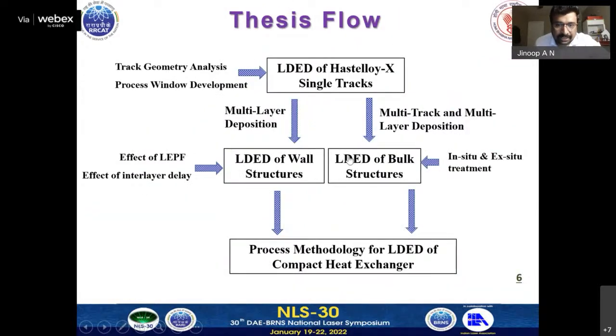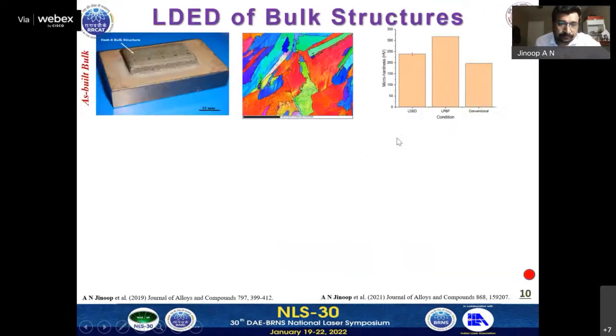Then the next study is on the bulk structures. Bulk structures are structures which are made of multi-track and multi-layer deposition. So for the bulk structures, we did multi-track and multi-layer deposition, and then we cut the cross-section and analyzed the samples. We could see that the microstructure is columnar in nature with a preferred orientation of the 100 plane, and the micro hardness and the mechanical properties were found to be higher than the conventionally built samples, but lower than the LPBF values, mainly because of the variation in the cooling rates.